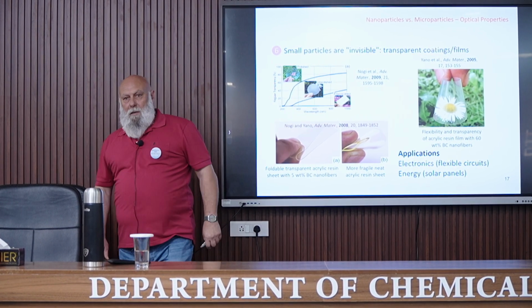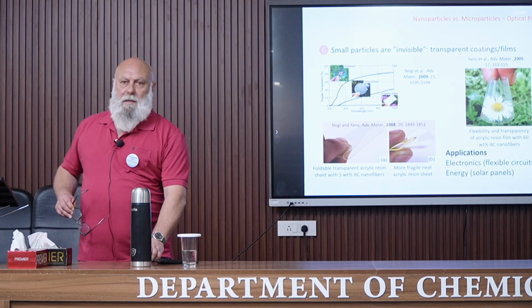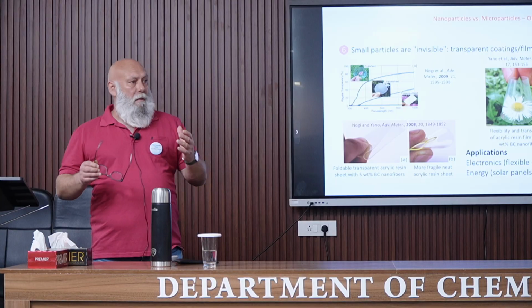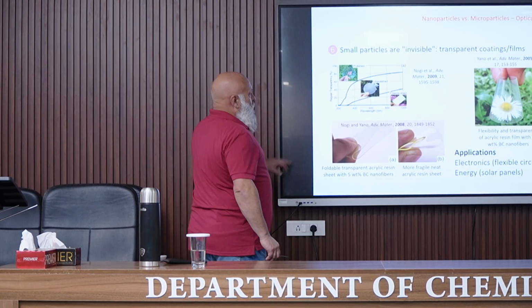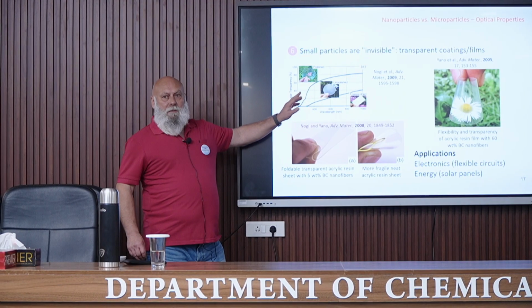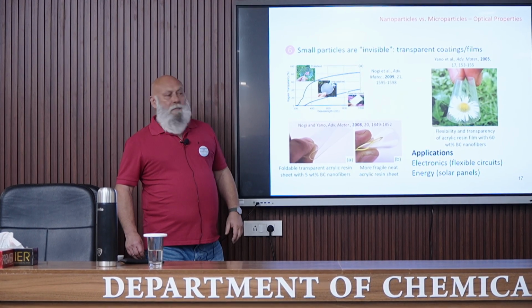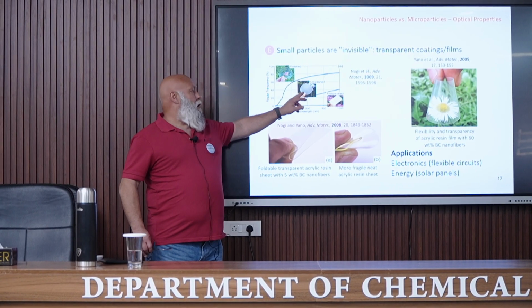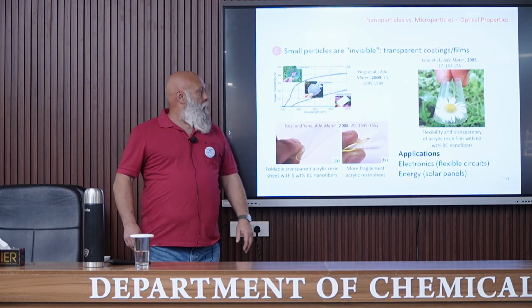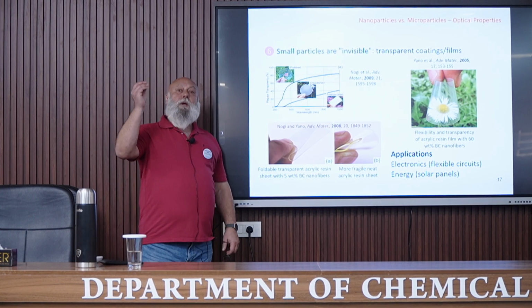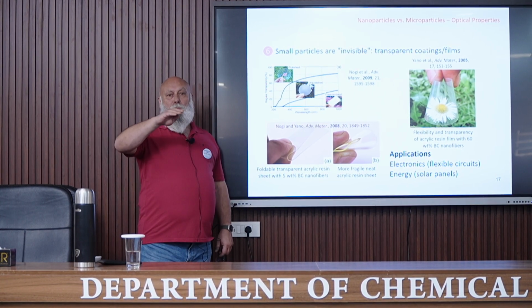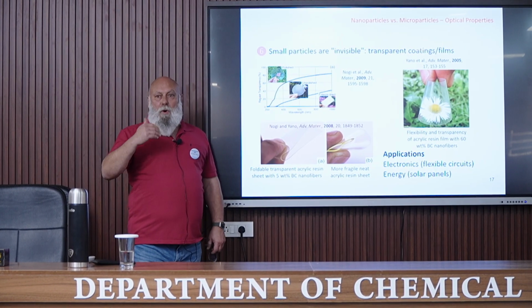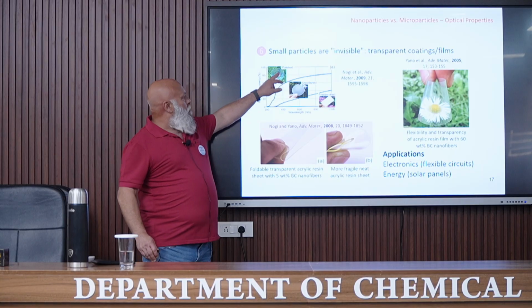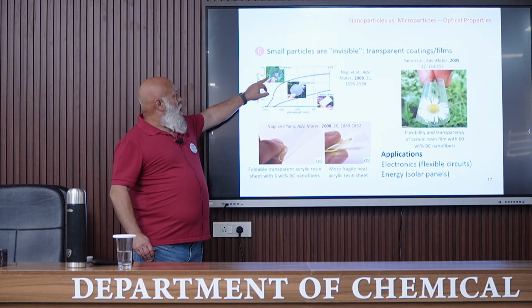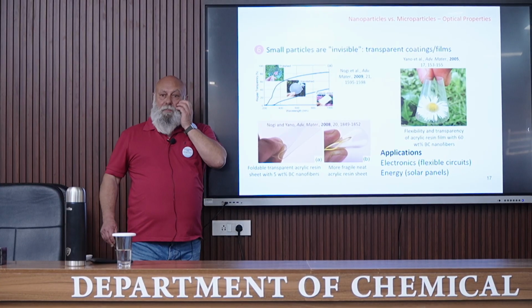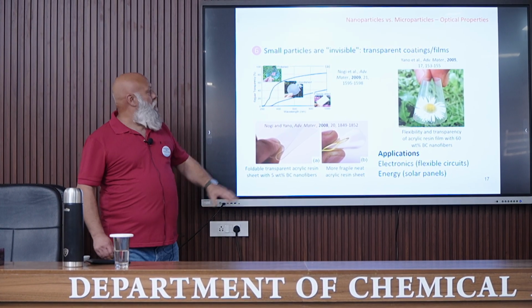The material is opaque, which is quite normal. We've seen previously that this material is porous. And because of this porosity, the material is opaque. To remove this porosity, it's possible to hot press the material. This material is obtained. It's more transparent, but it's not really transparent. The reason is that there is some scattering of light, due to the surface roughness. To remove this surface roughness, a polishing treatment has been applied. And you can see that a transparent nanopaper is obtained. So this material is made of only cellulose and it is transparent.